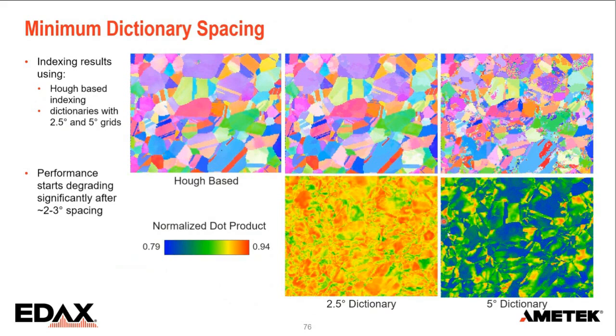And if we go even coarser, you have 5 degrees, you can see then the patterns become too different, and in a lot of areas we start to fail in the indexing, and we can't really get a good result anymore. So 2 or 3 degree is the maximum spacing that we can get.